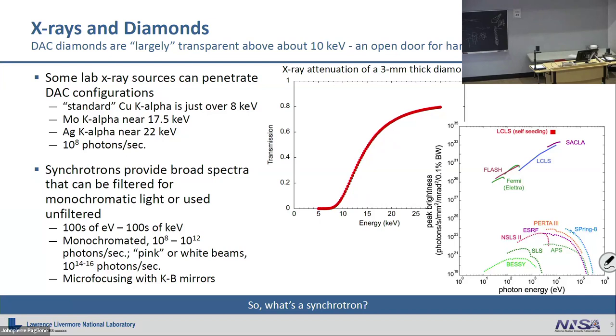Again, if you get up to some of the silver anodes or moly anodes, they'll be here, and so you can start getting some pretty good transmission. But you can also see pretty much everything over 20 kilovolts, the diamond becomes almost X-ray transparent by comparison. So everything up here, 15 kilovolts and above, is a cakewalk for experiments. Below 15 and down to about 6 is kind of doable, and things below 6 kilovolts start becoming extraordinarily photon starved because you're attenuating orders of magnitude in the diamonds.